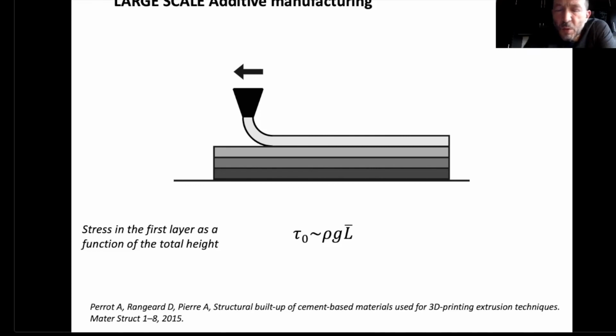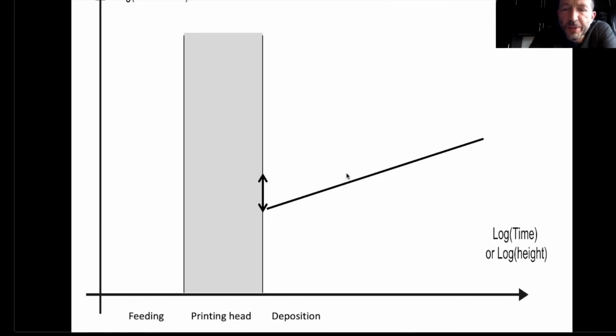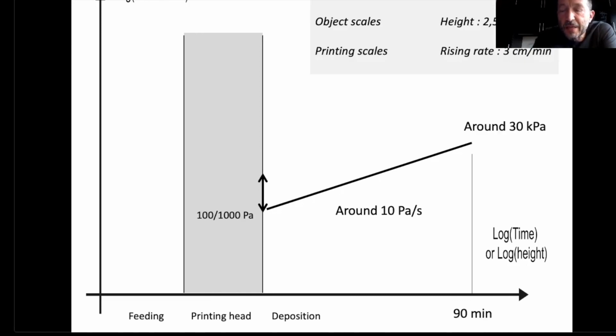But all in all, we can still apply the same relation between a gravity-induced stress, but this time it is increasing with the number of layers that have been printed, and the consistency inside the first layer. And this would require that the yield stress of the material increases linearly with the printing time or with the height of the printed element. So here we are facing a technology that requires different values for the yield stress, at least a value that is evolving with time, which is perfect for cement because cement naturally is changing with time as we discussed previously. However, the values you need to reach are quite high, so it means that this kind of change is mostly induced by some chemical hydration or some nucleation of minerals.